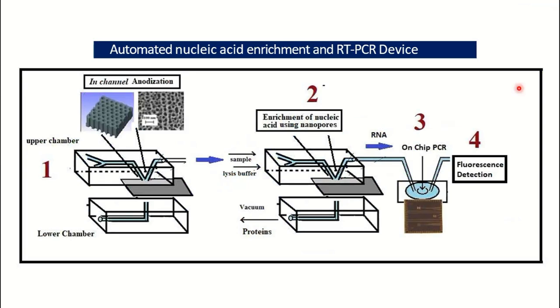So what we did here is devise a sandwich microfluidic device. In between, we have placed an aluminum foil, and this aluminum foil was anodized. Once it is anodized, you get this kind of nanoporous membrane, and we can directly isolate the nucleic acid in one step. So you lyse the cells, and the nucleic acids will stay on this, because, you know, putting a thread in a needle is very tough. So the long chain nucleic acid does not pass through the pore without any force.